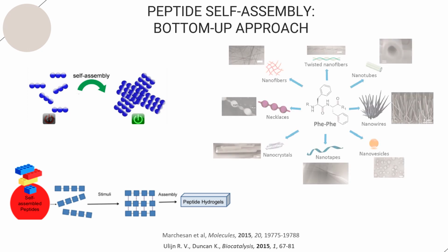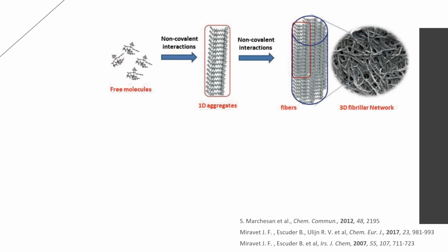But among the non-covalent interactions that collectively generate stable assemblies, pi-pi stacking plays a special role. These powerful forces, as exemplified in the short peptide motif of diphenylalanine, can be sufficient to enable access to a wide range of nanostructures. The self-assembly of a peptide is a hierarchical process where free peptide molecules self-assemble into one-dimensional aggregates, which then form fibrils that wrap around larger fibers intersecting to form a gel.